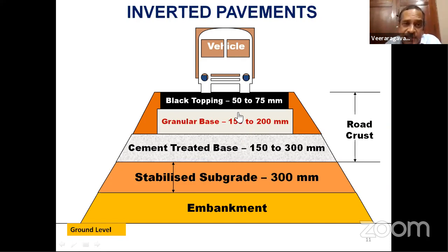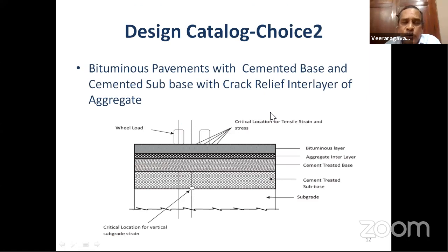But there are issues and concerns even in inverted pavements. But the advantage is that when you have an inverted pavement, you can reduce the thickness of the bituminous layer and hence the cost of construction as well. So the IRC in 2012 brought an alternate design, wherein they introduced a cement-treated subbase and a cement-treated base. But remember, this layer is likely to crack. So they have already suggested an aggregate interlayer, which will retard, not prevent, the appearance of cracks at the bituminous layer.